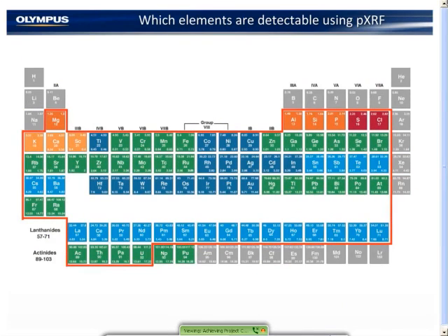Our element range begins at magnesium, and the heaviest element we add to a standard element list is uranium. Not all of these elements are typically calibrated on an analyzer. Our experience has led us to include 34 elements that are typically required, but we can customise elements where required depending on spectral overlaps. For example, gold can be analysed by our XRFs, but not below 5 parts per million, and can produce false positives in the presence of zinc, tungsten, and arsenic, because it sits in a very crowded area of the spectrum. So these things all need to be considered.